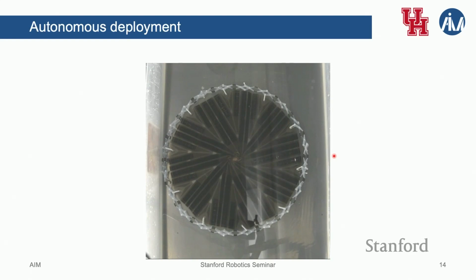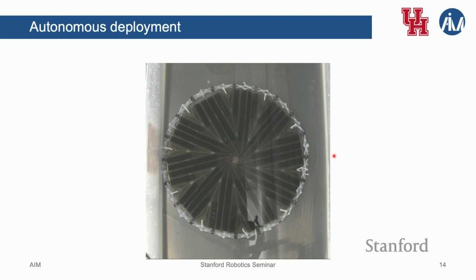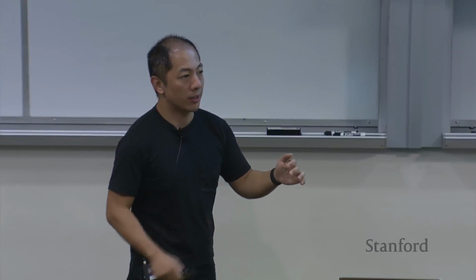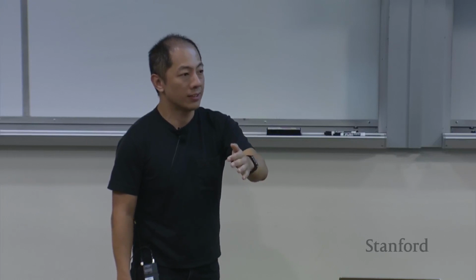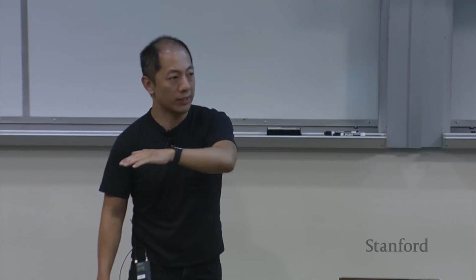Does the rate of change in temperature affect the mechanical properties, or just the rate of expansion? So there's thermal conduction that we're not accounting for, but the stuff is very thin. Right, so it's not a continuous change. So if you imagine the Young's modulus, it's pretty much increasing very shallowly until it hits the glass transition temperature, at which it drops significantly, and then it goes as well. Yeah. So we utilize this nonlinearity, this continuous change to affect this.